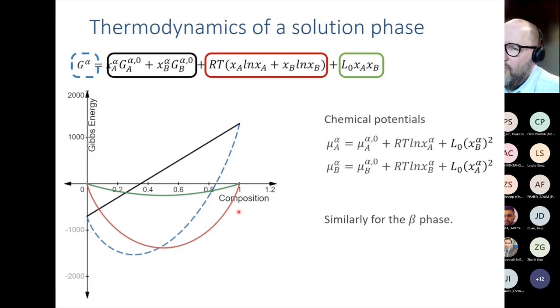So if we add all of these terms together, the green curve at the bottom represents the contribution of the excess term. And that's the simplest model we can think of for that. There's more complex models for that. That's something for a discussion on another day. But if we add these three up, we actually get the blue dashed curve below. And the assumption, and it's a rather good one, is that this is valid whether we are in equilibrium or not. This is describing simply the free energy of a given phase at a given composition and a given temperature. And this is the foundation for all of the things that will follow, and that's very important to keep in mind. So this remains valid even if we're off equilibrium.